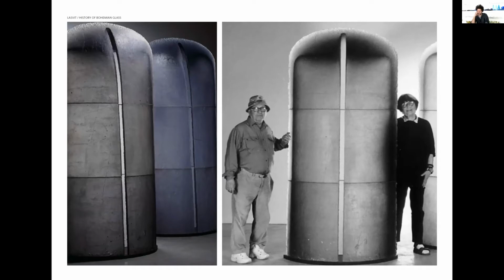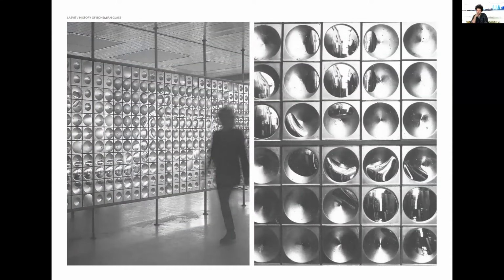And imagine that such a block you would cool for, for example, half a year to be able to take it out of the kiln. So the whole process can be really time demanding, and it's all about slow cooling the blocks so they won't crack. This is some of the samples of their work, amazing wall dividers made with this technique.